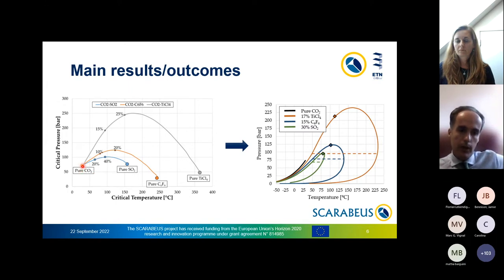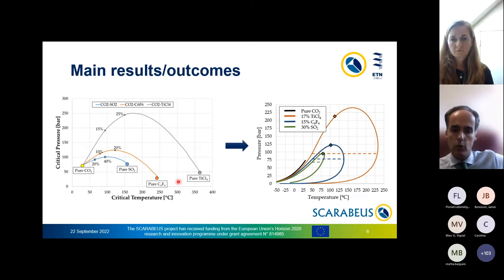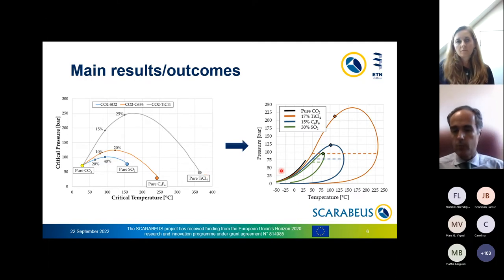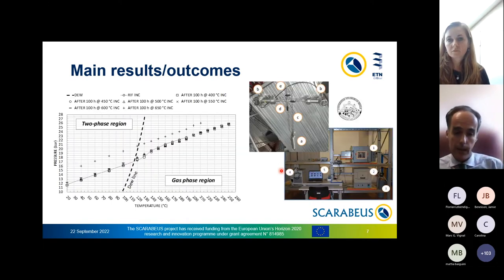We start with raw CO2, so pure CO2, critical pressure and critical temperature well known by all of us. If we add different dopants in different quantities, either sulfur dioxide, hexafluorobenzene, titanium tetrachloride, these are some of the dopants we are currently considering, we can change critical temperatures. So if we increase ambient temperature, we are still able to accomplish our objective. Once we identify the optimum mixture, and there is not a universal optimum mixture, because we can tune our mixture and tailor it to the particular location of the power plant, then we produce these pressure temperature saturation line diagrams based on experimental results. And this is what you've got in the next slide.